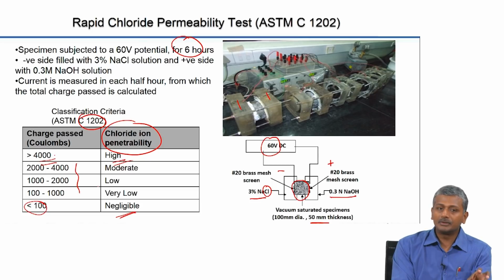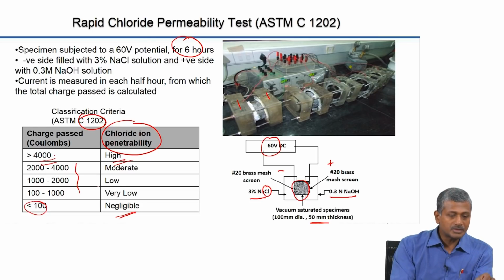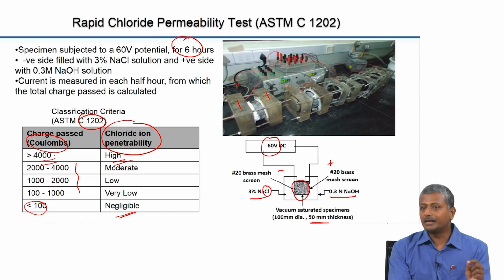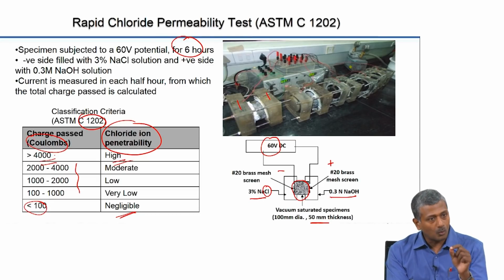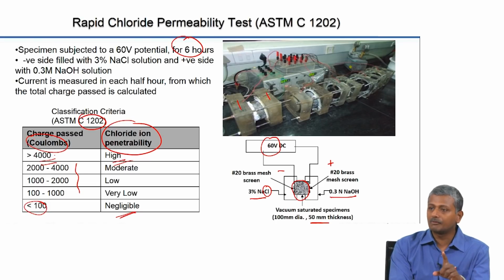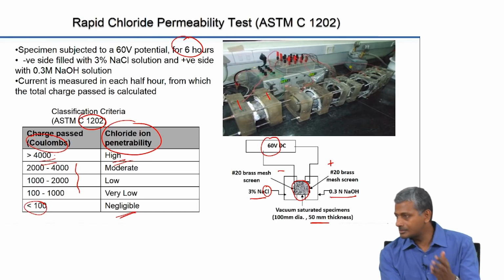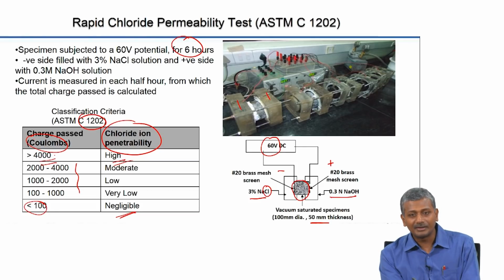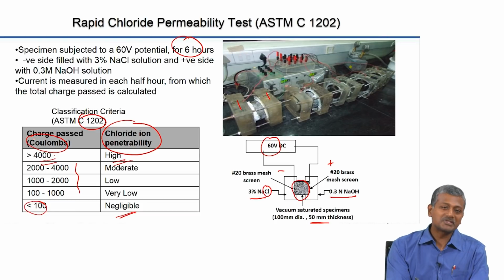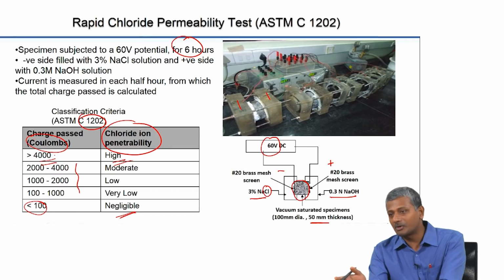So again, although something quantitative like the coulomb charge passed is calculated through the concrete, the interpretation of the result is still based on the quality of the concrete. That is a very important thing for you to remember. When you measure the strength, you report the strength. You do not say the concrete is nice or good if the strength is 40, or my concrete is excellent if the strength is 47.5. No, we just say 47.5 means 47.5 strength.